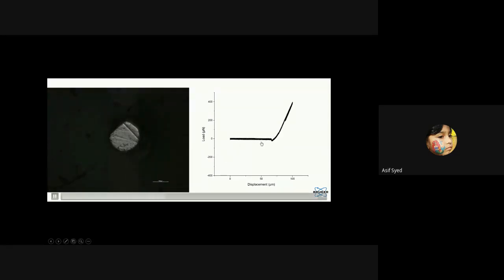What you see over here is the load displacement curve, and you can see that it's a small jump in contact, load and unload. When you unload, you can see a large pull off, mainly because of the adhesion. So both this video as well as this load displacement curve are totally synchronized. If you do 30 frames per second, you've got 30 points per second, and frame by frame you can analyze the video along with the load displacement curve that you make a measurement. So this way, you can also have an optical measurement where you can measure the size of the contact.